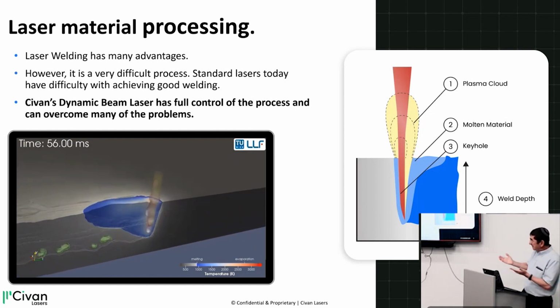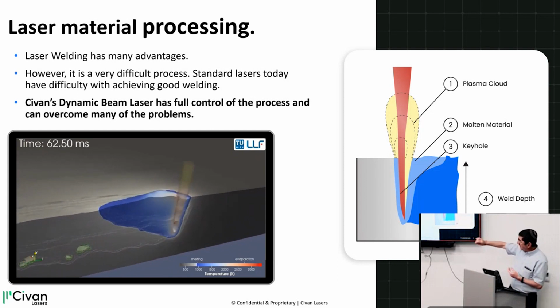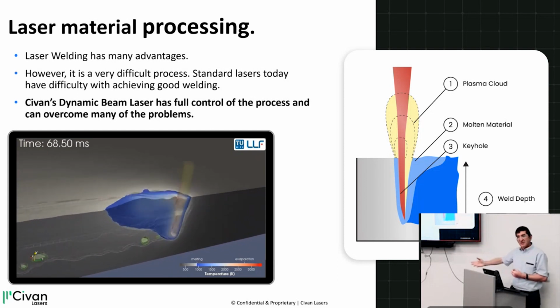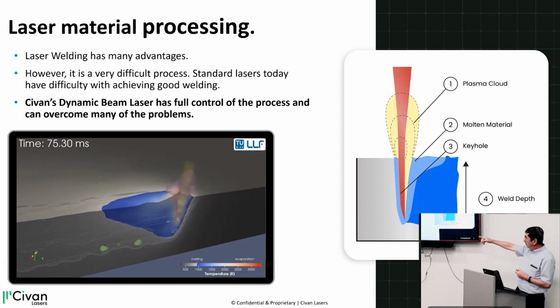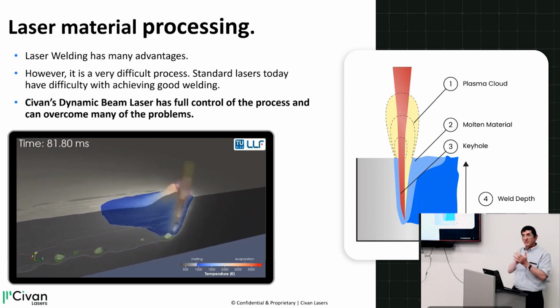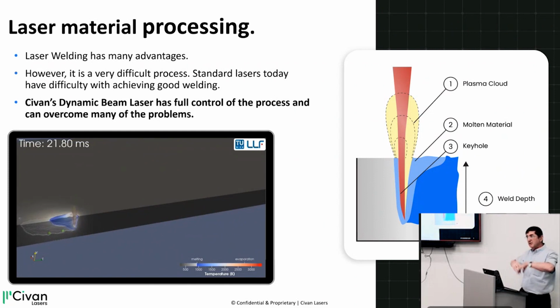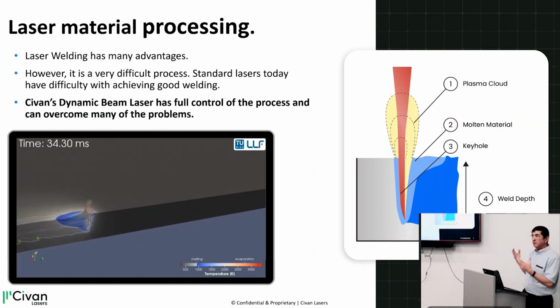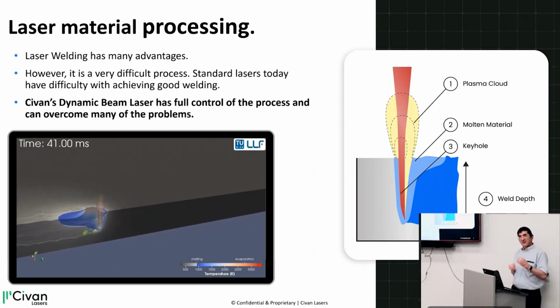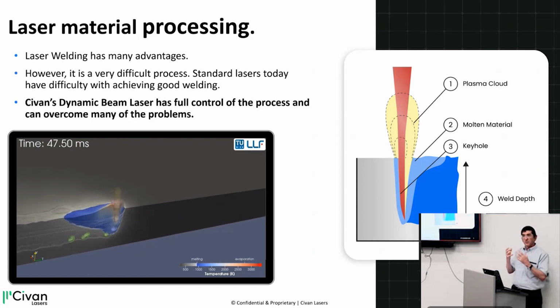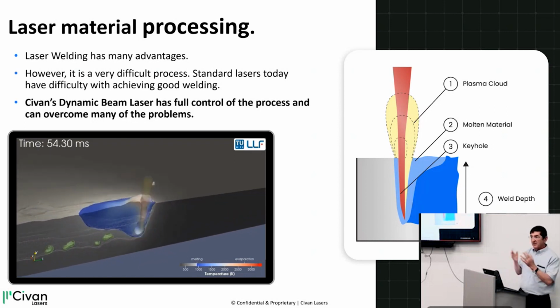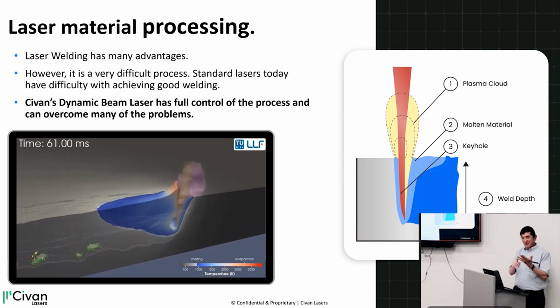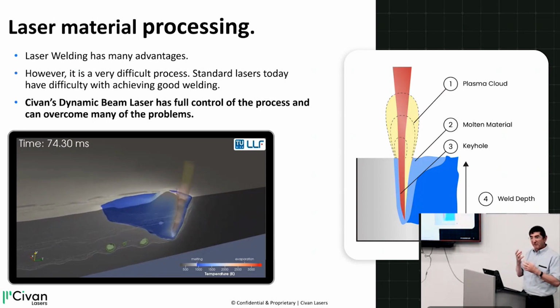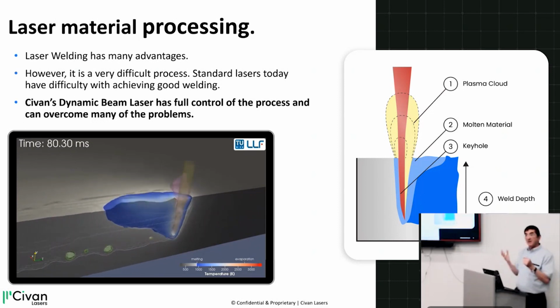And really what happens in reality is, like you see here, that sometimes material falls and collapses the keyhole, and then you have porosity. You see the bubbles that are captured inside the material. You have spatter because things just fly out. And probably the worst thing is that you don't control the phase of the metal that it resolidifies to, right? So when the metal resolidifies, you can have different phases of the metal, and you can create cracks, you can create brittle phases of the metal. Sometimes it can become too hard.